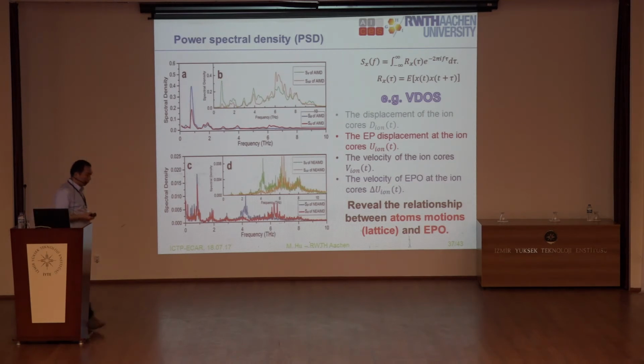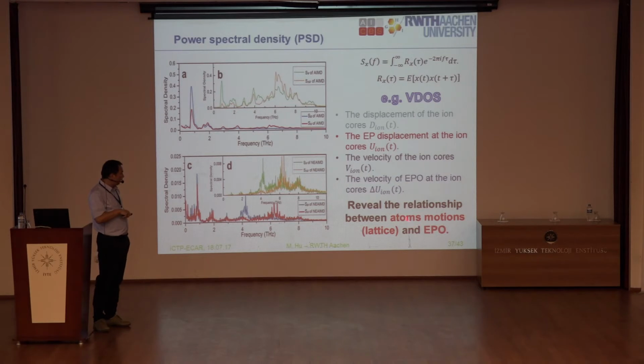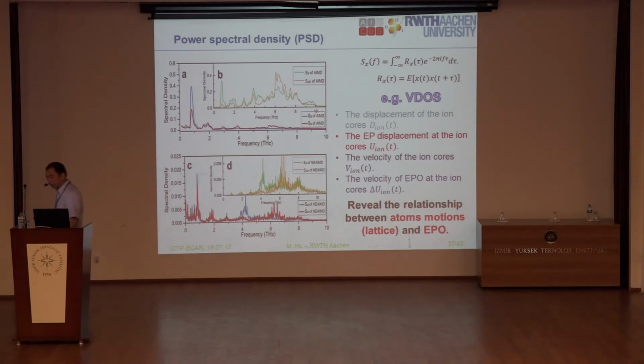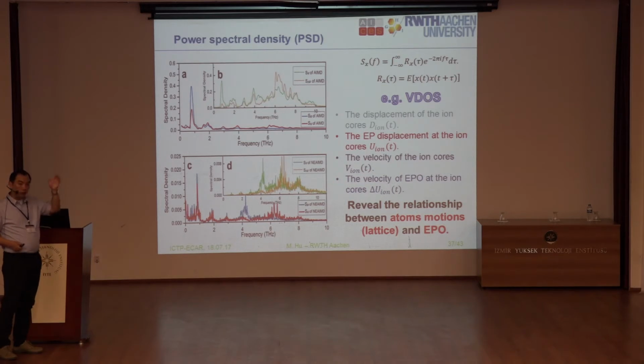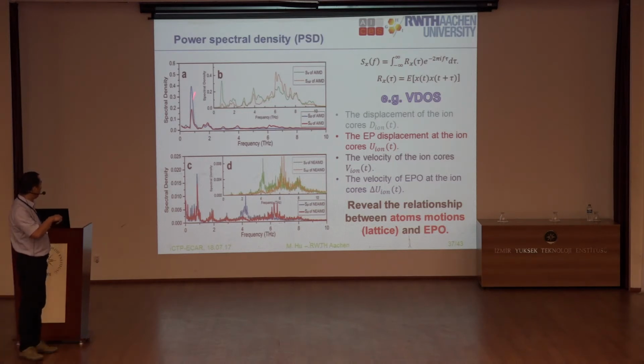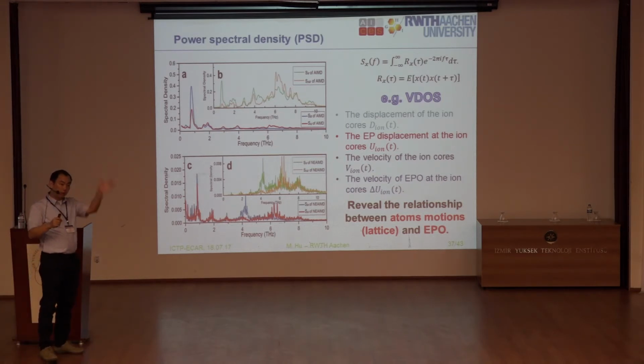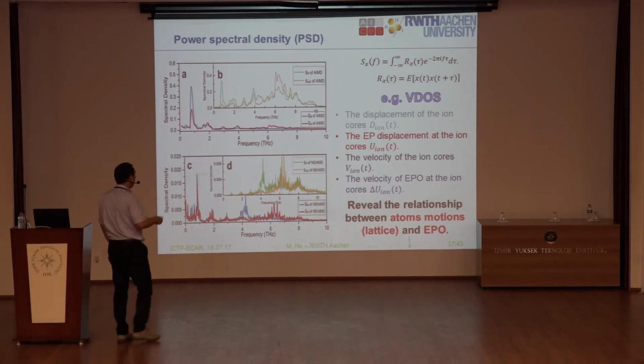First, we have to get the relationship between the atomic motion and this electrostatic potential vibration. It means that we have to prove that in space, the electrostatic potential oscillation is induced by the vibration of the nuclei. That's very easy to prove. For example, we calculate the peak of this EPO, the electrostatic potential oscillation, and we do the Fourier transform to get the frequency dependence, and then you can see the peak. And then we do the same thing for the velocity of the ions, right? And we found that the peaks overlap with each other very well. So it means that once you have the electrostatic potential vibration in space, it is exactly because of the thermal vibration of the nuclei. I think this is very easy to follow.